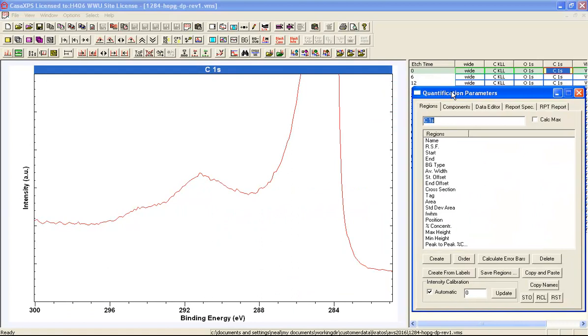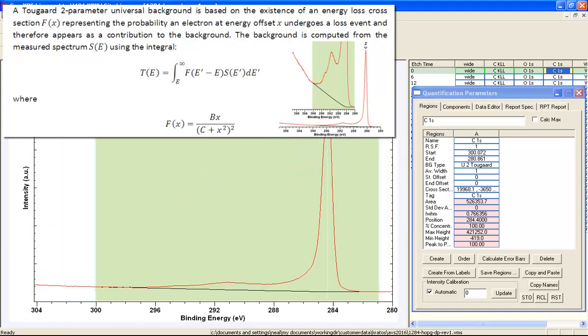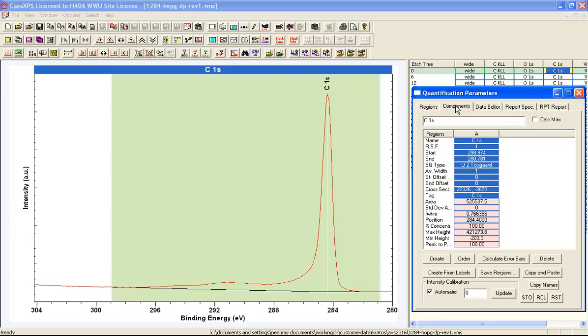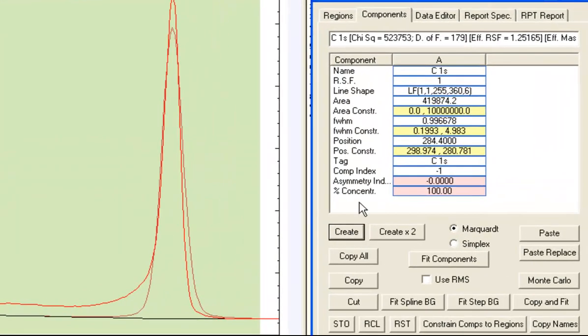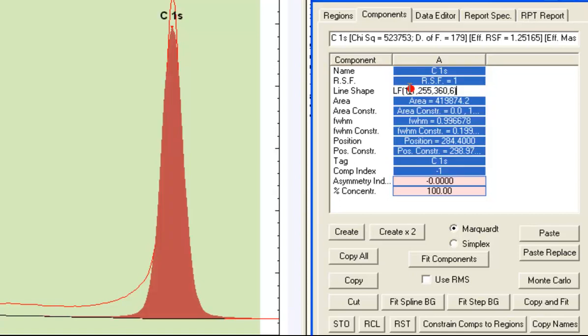So we will require more than one peak to construct this peak model, but what we will certainly need is some form of asymmetric line shape. We'll start by putting a background on, which is going to be a Tougaard background. And then we'll start to add synthetic components, and we're going to use this LF line shape. And the LF line shape has a pair of parameters,